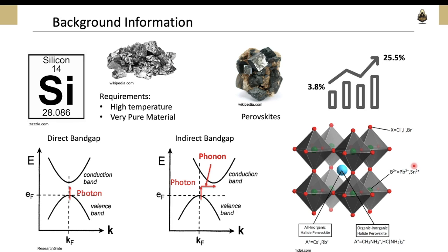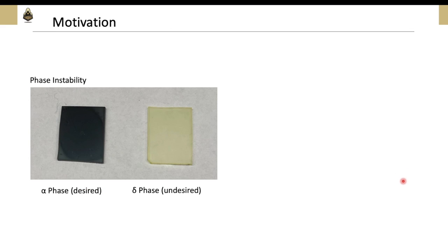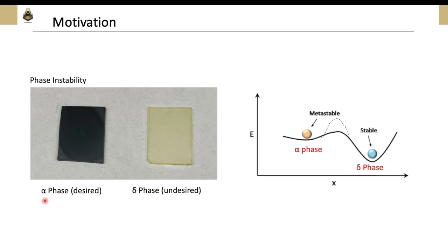Formamidinium lead iodide is used in the highest performing perovskite solar cells due to its near ideal bandgap. However, the photovoltaic crystal phase of formamidinium lead iodide is only metastable. At room temperature, the non-perovskite yellow delta phase is thermodynamically more stable than the desired photovoltaic black alpha phase. By increasing the activation energy required to transform to the delta phase, we're able to kinetically trap the desired phase of FAPbI3 perovskite. Currently, the best perovskite solar cells degrade in about 6 months, which has delayed their commercialization.